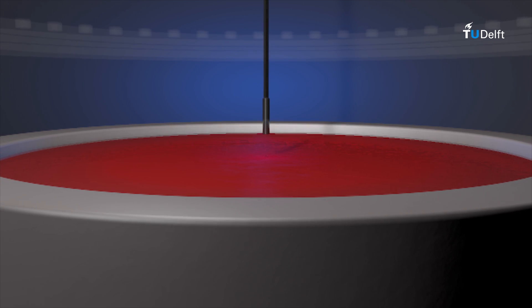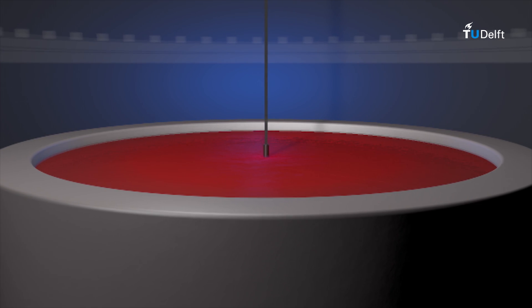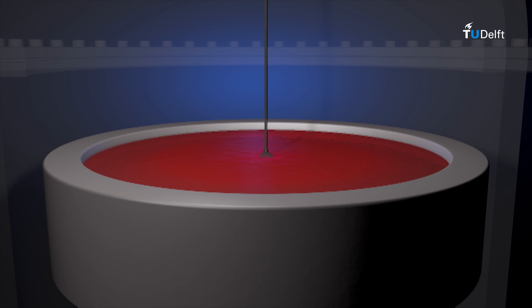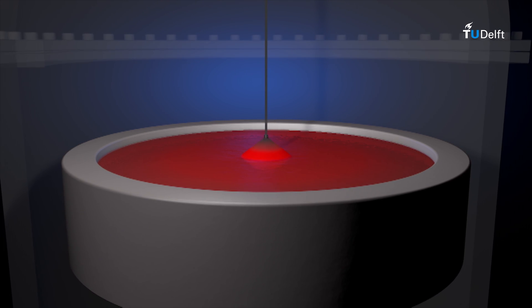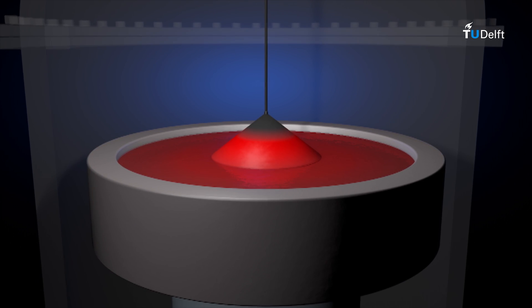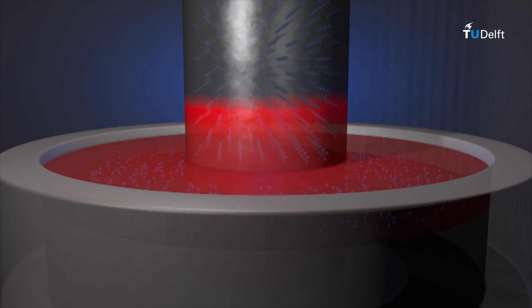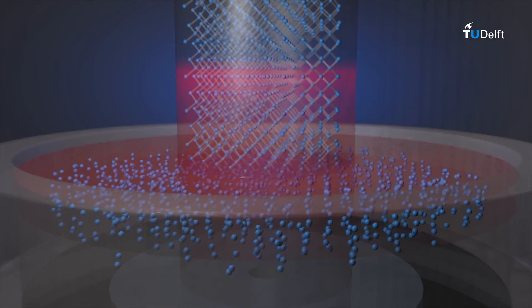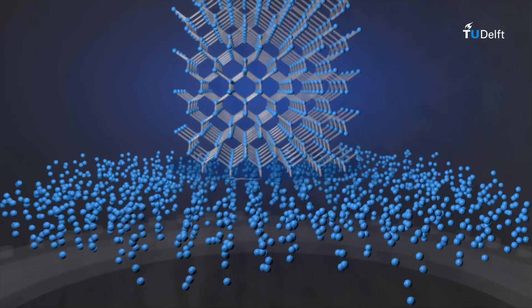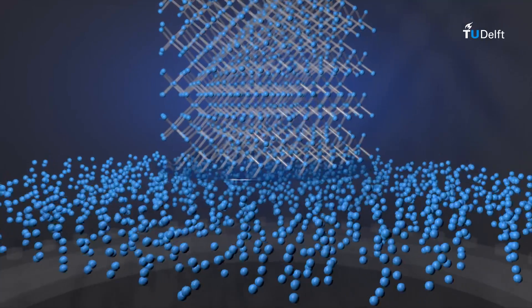The Czochralski method is used to grow single crystal silicon. Highly purified silicon is melted in a crucible at typical temperatures of 1500 degrees Celsius. Intentionally, boron or phosphorus can be added to make p-doped or n-doped silicon respectively. A seed crystal mounted on a rotating shaft is dipped into the molten silicon; the orientation of this seed crystal is well defined — either a 1-0-0 or a 1-1-1 orientation. The melt solidifies at the seed crystal and adopts its orientation. The crystal is rotated and pulled upwards, allowing the formation of a large single crystal cylindrical column from the melt.